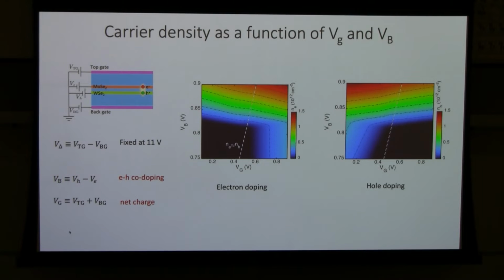If it's large enough, it will induce electron-hole co-doping. And we can also control the symmetric gate voltage that controls the net charge density. And these two maps basically show the electron density and the hole density as a function of the bias voltage and then the gate voltage. So basically what we can understand is, if you do a horizontal line cut here, basically we see that